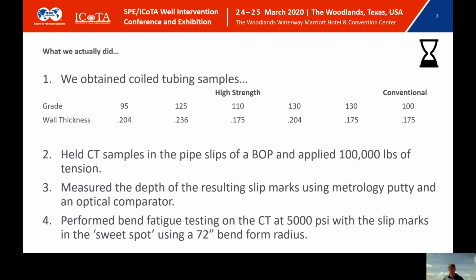That was the plan. This is what we actually did. Procuring the samples from some of the mills was a little more difficult than we anticipated. In the previous slide, I noted that we were targeting 188, 190 wall, and you'll note that not one of our samples is that wall thickness.